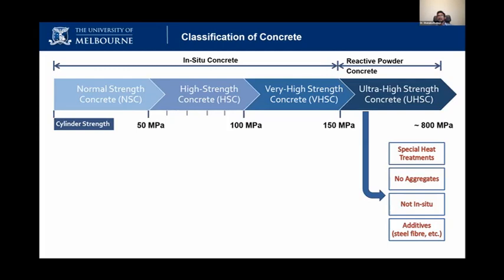But the challenge is how to get strength around 100 to 150 using naturally available aggregates. Then we can produce concrete of even more than 150 megapascal. We call this reactive powder concrete. There are companies very famous for this type of cement, very popular in Europe as well because of precast, like bridges and precast structures. That can be developed without aggregates, because the aggregate is the weaker link in the concrete, particularly the interface between aggregate and the mortar, which we call the ITZ, interfacial transition zone.